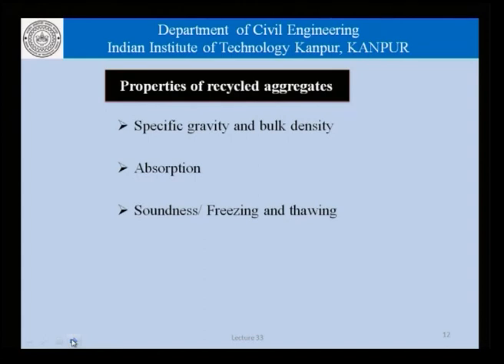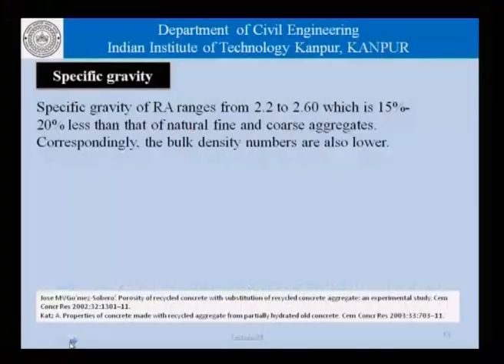The specific gravity, bulk density, absorption, soundness in freezing and thawing, these are some of the qualities of the aggregate which will be relevant whether we are using recycled aggregate or normal aggregates. As far as specific gravity is concerned, the specific gravity of recycled aggregates ranges from about 2.2 to 2.6, which is about 15% to 20% lower than that of natural fine and coarse aggregates. And correspondingly, of course, the bulk density numbers will also be lower.